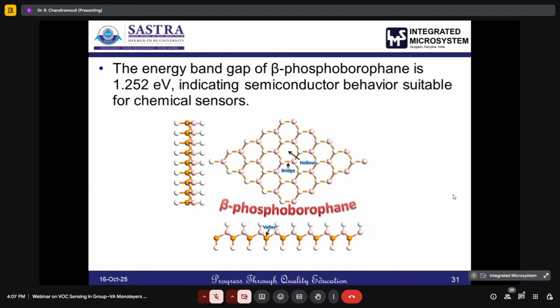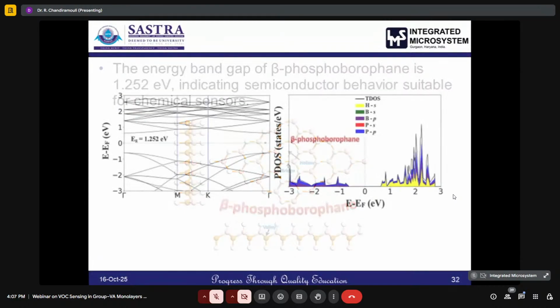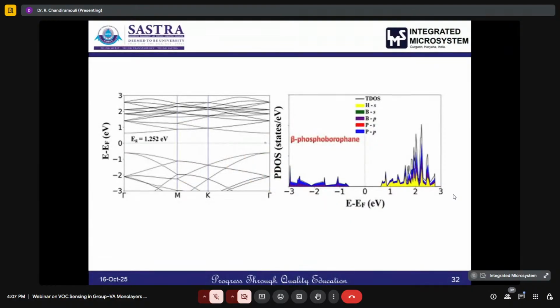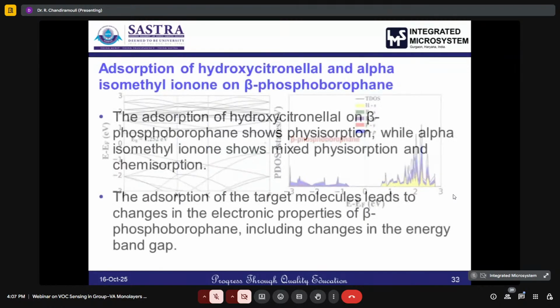So here you can see the structure of beta phosphoborophane. You can see that in the vertical direction, the white balls are the hydrogen. So the phosphorus and the boron, the borophane, is being hydrogenated vertically to open the band gap. Here you can see the band structure and the PDOS spectrum obtained from the QuantumATK package, and you can see that the energy band gap at the gamma point is 1.252. Here also in the PDOS spectrum we can see the energy band gap of 1.252, and the hybridization of boron, hydrogen, and phosphorus atoms, the sp orbital, is also shown with a different color gradient.